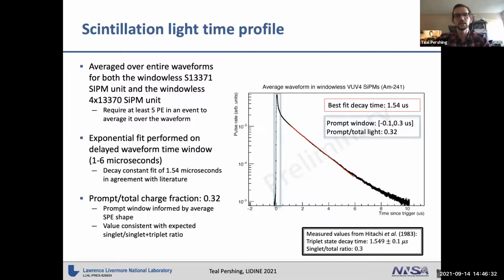And we required at least 5 PE in an event to make sure that we're not picking really any of the dark pulses for the most part. And so the average waveform shape is shown here on the right. First we just did an exponential fit in the delayed window to see if we're getting the expected slow scintillation component that you want for argon. And so we measured for a first fit 1.54 microseconds, which is good to see.